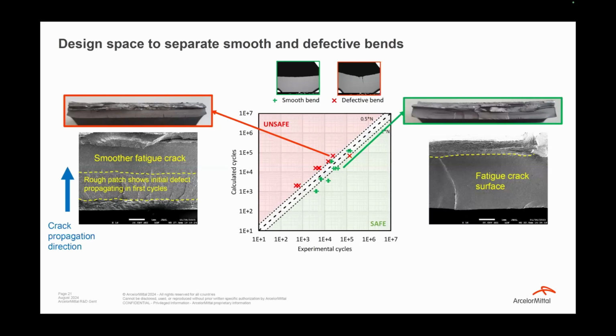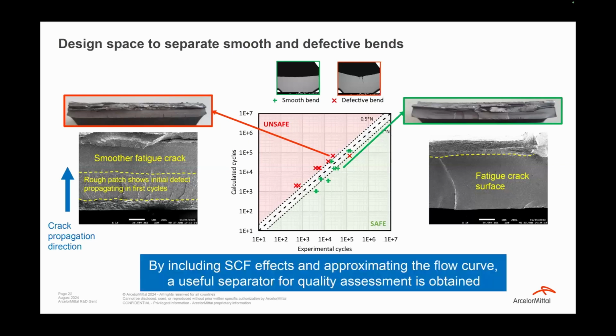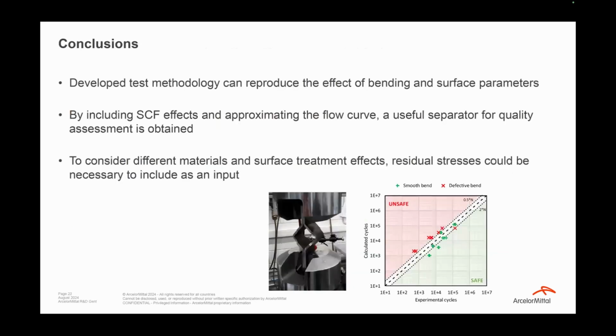And if it's a good bend, if it's a smooth bend, then you can clearly see the initiations, and then you have a nice smooth fatigue crack surface. So by including the stress concentration effects and approximating flow curve, it gave us a useful separator in quality assessment of our material. So this will be the main conclusion that I would like to highlight. And also just to remind that the test methodology itself can reproduce the effects of bending and surface parameters. Now we are extending this to consider different materials and surface treatment effects.